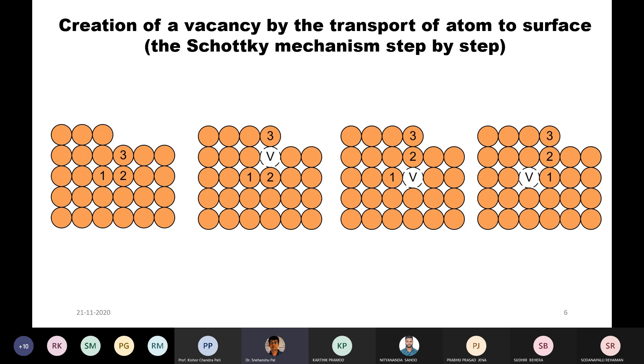Note that we are considering the limit of non-interacting defects here. Since the equilibrium concentration of vacancies is typically small, the enthalpy change due to broken bonds and the entropy change due to irregular vibration can be considered to vary linearly with vacancy concentration. Introducing a vacancy also gives rise to considerable change in configurational entropy because of increased possibilities of arrangement between components and vacancies.